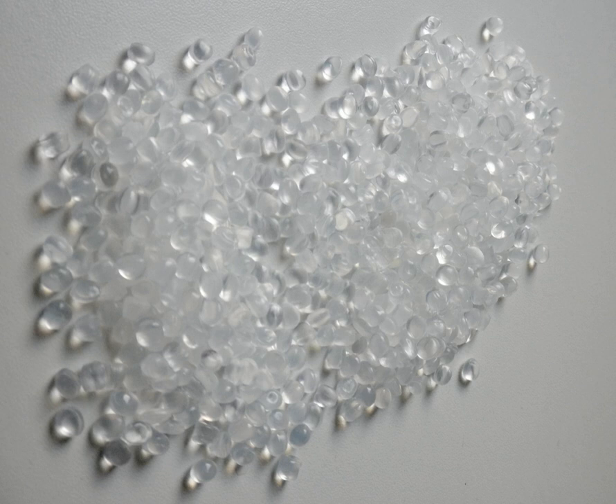HDPE is defined by a density of greater or equal to 0.941 grams per cc. HDPE has a low degree of branching. The mostly linear molecules pack together well, so intermolecular forces are stronger than in highly branched polymers. HDPE can be produced by chromium, silica catalysts, Ziegler-Natta catalysts or metallocene catalysts. By choosing catalysts and reaction conditions, the small amount of branching that does occur can be controlled.